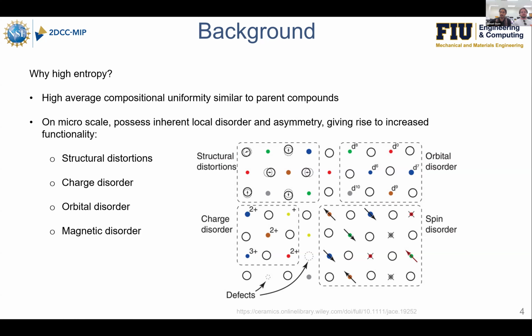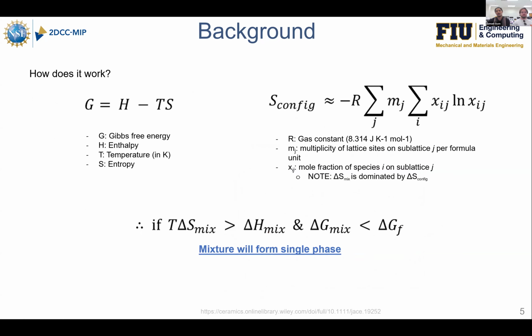In our case, we wanted to fine tune the band gap of the high entropy materials with respect to their parent compounds. So to explain a little bit of how high entropy works, essentially by adding a lot of these different elements into the compound, a lot of literature suggests that the magic number for really minimizing the Gibbs free energy of the system is 6 to 7 elements.